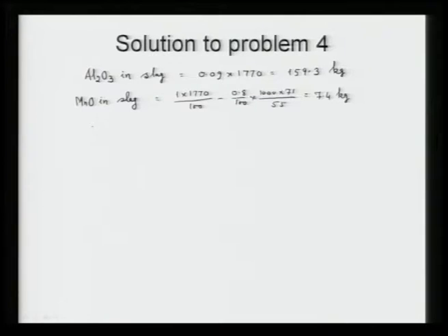Now, if you say Y kg is the slag amount, then we can write down 0.64 Y will be equal to summation of say 347.7 plus 159.3 plus 7.4.